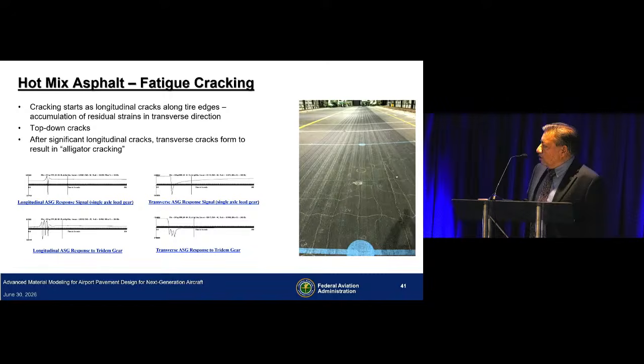But one of the things to note here is that as the wheel approaches, you get your tensile strains, and most of those strains are recovered. So you do not have any significant amount of unrecovered strain or permanent strain. When you look at the transverse strain gauges, that's where you start seeing some strain accumulation. And this is for single axle and 3 axles. And what you see is as each of these axles approaches, now you start seeing accumulation of strains. And it is this accumulation of transverse strain that results in the longitudinal crack in your pavement structure.